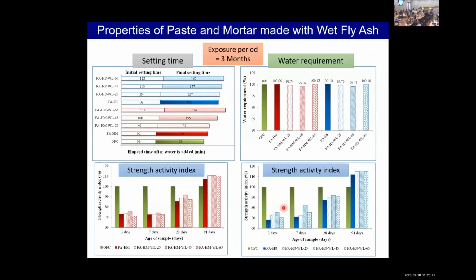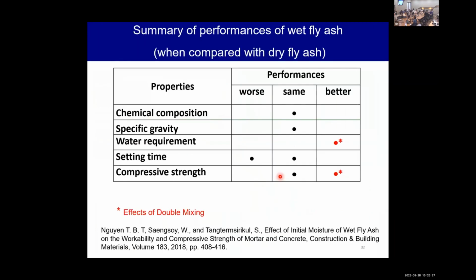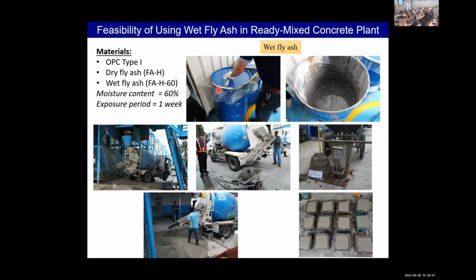So we made the fly ash wet, and conducted tests comparing wet and dry fly ash. We can see that the wet fly ash has similar properties to the dry fly ash, but also gets better performance, like water requirement and compressive strength. This comes from the effect of double mixing from the pre-existing water in the fly ash. The mechanism was also published in one paper. And we also studied the feasibility of using wet fly ash in a ready-mix concrete plant, using wet fly ash and dry fly ash.